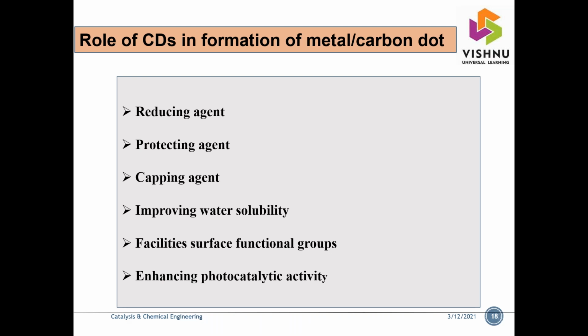Here we can see this carbon dot acts as a reducing agent for the metals, a protecting agent to avoid agglomeration, and also a capping agent. It improves the water solubility, facilitates the surface functional groups, and enhances the photocatalytic activity.